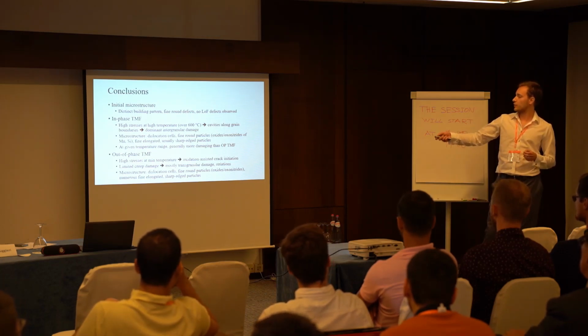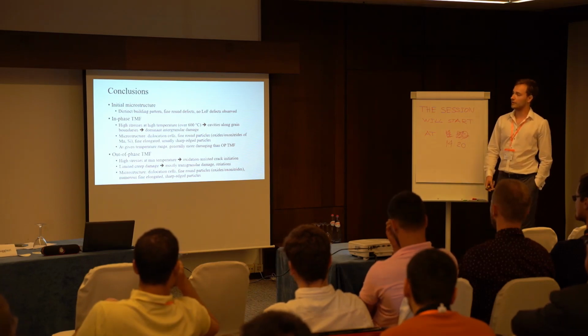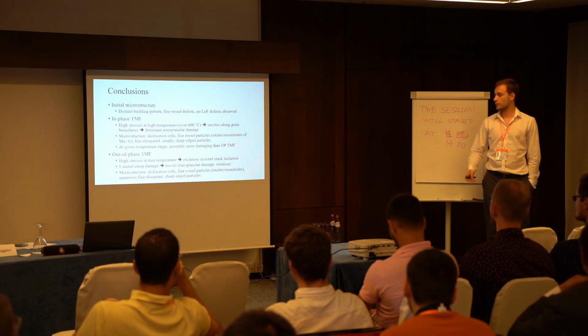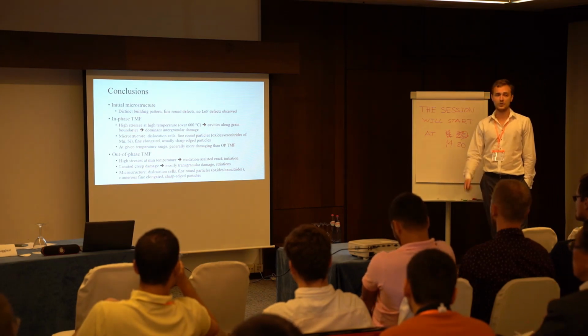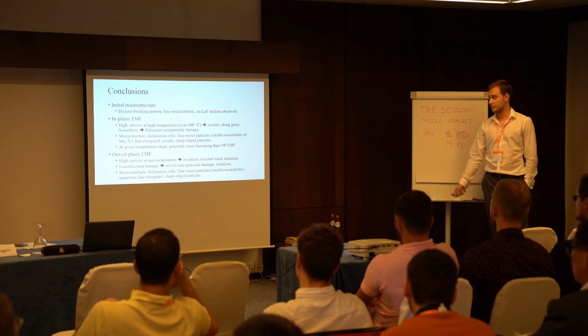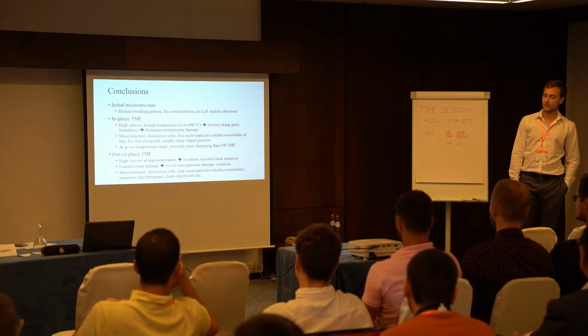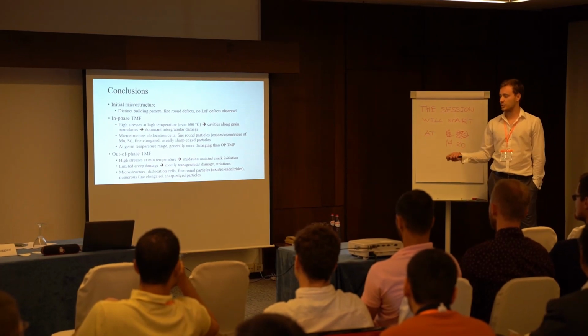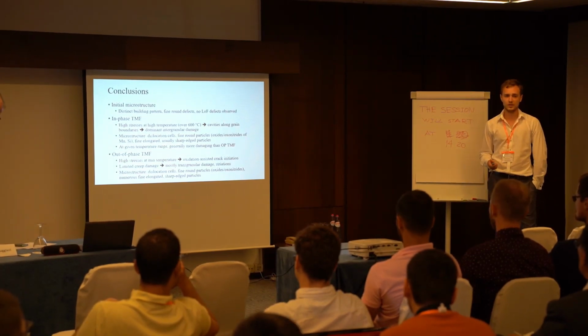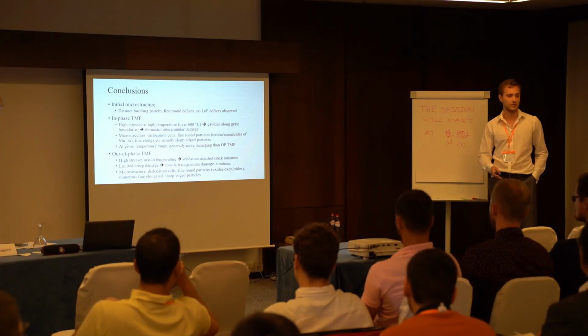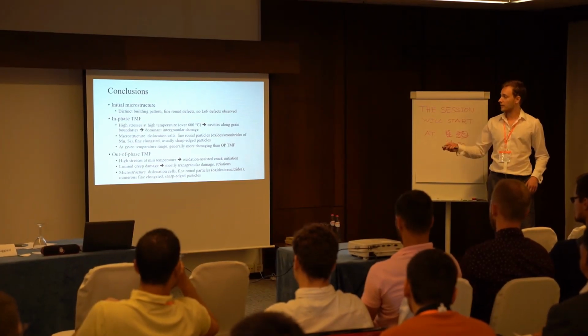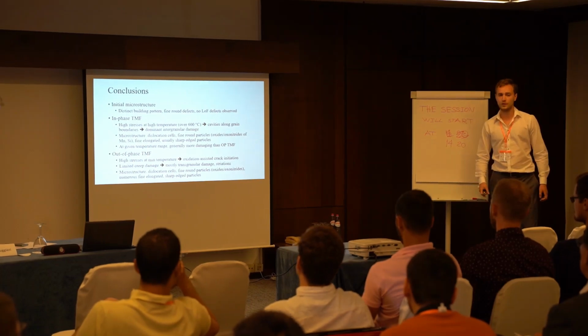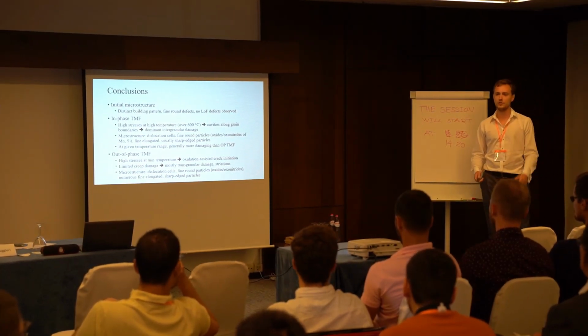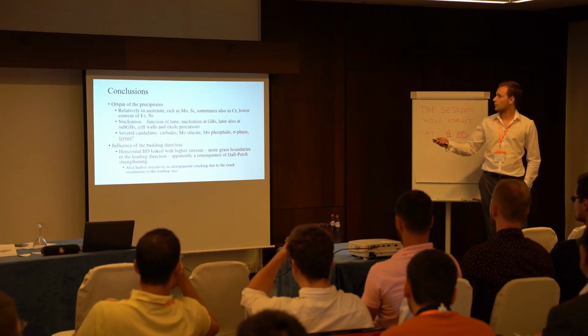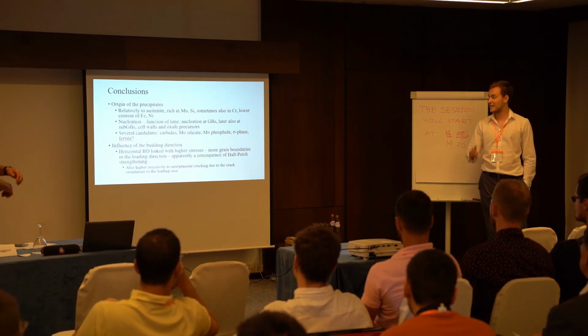In case of out-of-phase thermomechanical fatigue, we had, on the other hand, high stresses at the minimum temperature, which led to oxidation-assisted crack initiation. We had limited creep damage, which led to mostly transgranular damage with striations at the fracture surface. The microstructure consisted of dislocation cells, most of which were stable. In some cases they were rearranged, in some cases even completely destroyed. We had fine round particles and numerous fine elongated sharp-edged particles rich in molybdenum, silicon, sometimes also chromium, and with lower content of iron and nickel.